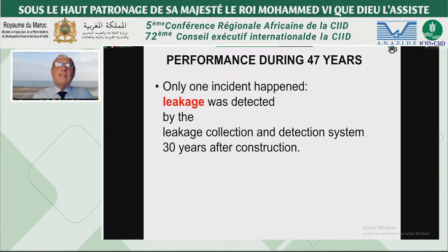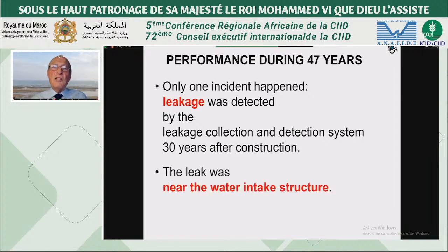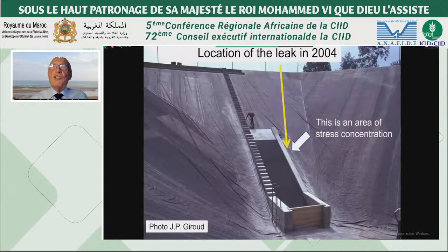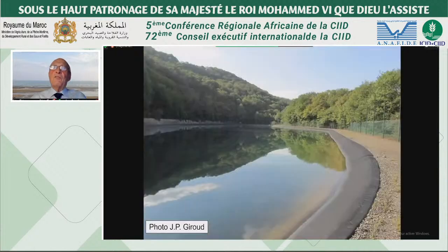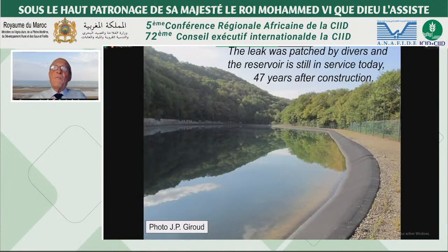Only one incident happened. Leakage was detected by the leakage collection and detection system 30 years after construction. The leak was near the water intake structure, which is not surprising because this is an area of stress concentration. The leak was patched by divers and the reservoir is still in service today, 47 years after construction.